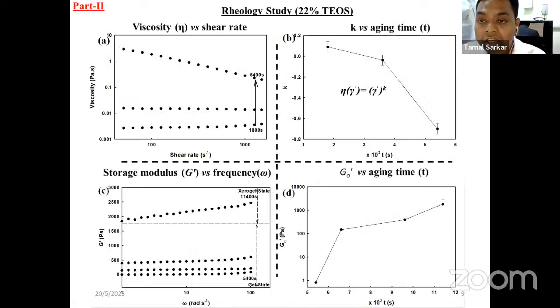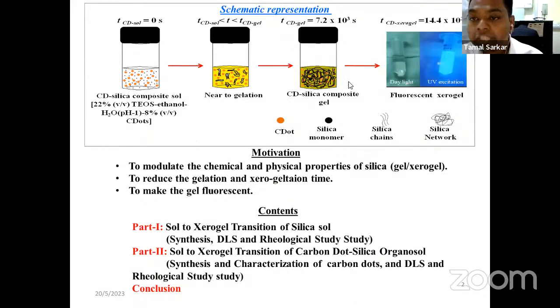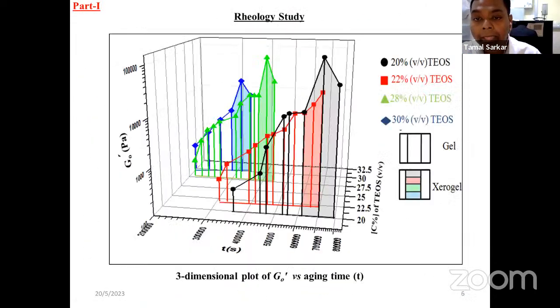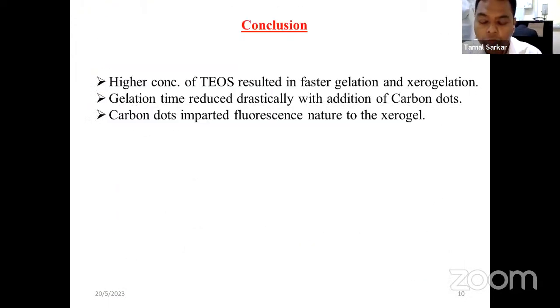In the first slide, I showed in the schematic diagram that this is the gel. It is a gel inside the Eppendorf tube, which is kept on a table, and you could see that the gel is in the lower part of this Eppendorf tube, and under daylight we could see no fluorescence. When this tube is kept under UV excitation, the gel fluoresces. The fluorescence properties came from the fluorescence properties of the carbon dots. This is one major conclusion, and thank you all.